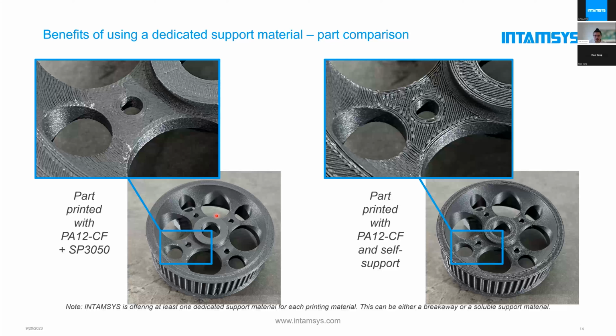Yeah, because if you are looking into the part afterwards, you would really see on the left side, it's almost impossible to see the lines of the printing process, and also in the overhang you really see a smooth surface, and you have a very low porosity in this. Yeah, this is very important if people touch parts or parts need to be cleaned or painted or whatever. Too high porosity is a problem because you cannot apply filler. You need to sand them a lot before, and so on. Yeah. So you can see this is the bottom side, and I think this is really a good quality level that you can achieve with it.